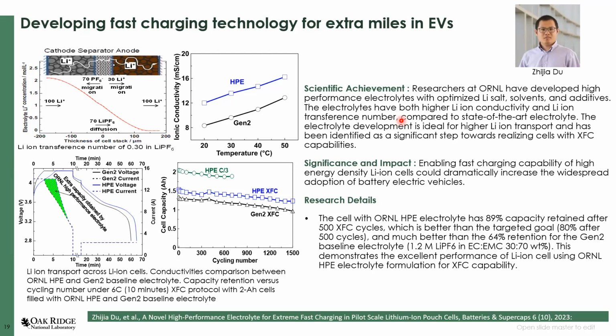Additionally, it turns out that most of both the cathodes and the anodes are not in their thermodynamic state. They are far away from thermodynamic stability, and the electrochemical stability window of the electrolytes does not cover the entire range over which they need to be stable. So there are a lot of interactions that take place between the electrolyte and the electrodes. Tuning that also helps in keeping a pristine, good electrode-electrolyte interface. So electrolyte engineering is key to getting good batteries, particularly fast charging batteries. Zhijia has been very successful in developing electrolytes for fast charging, which meet or exceed the requirements put forth by the Department of Energy.